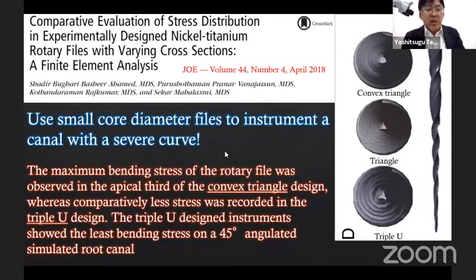And they found the maximum bending stress of the rotary instrument was observed in the apical 1/3 of the convex triangular design, whereas comparatively less stress was recorded in the triple U design. So the triple U design instrument showed the least bending stress on a 45-degree angulated simulated root canal. So if you don't want to break an instrument, use an instrument with a triangular or triple U shape cross section. So this is what they are telling.